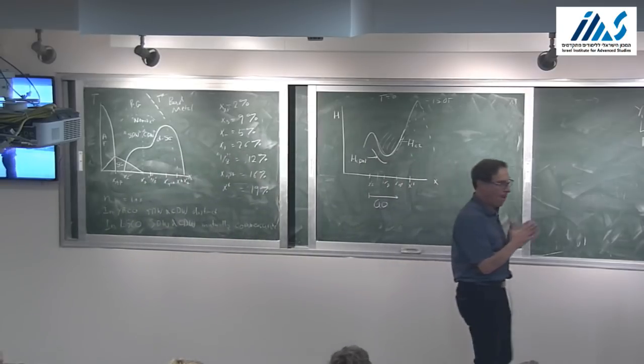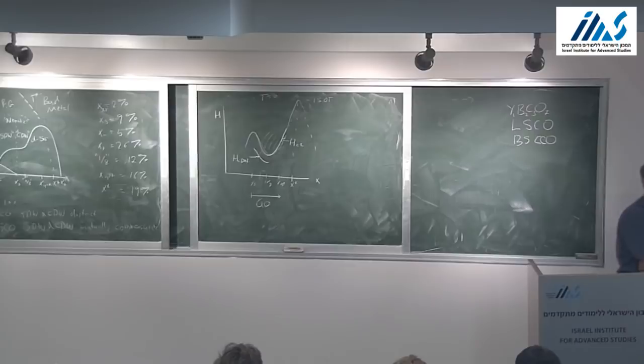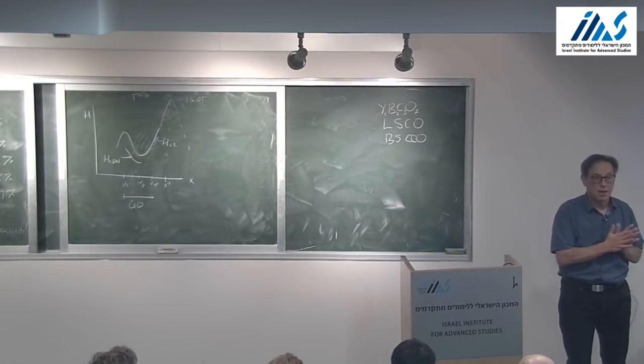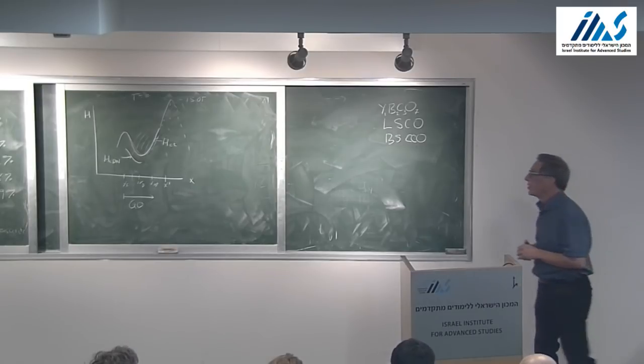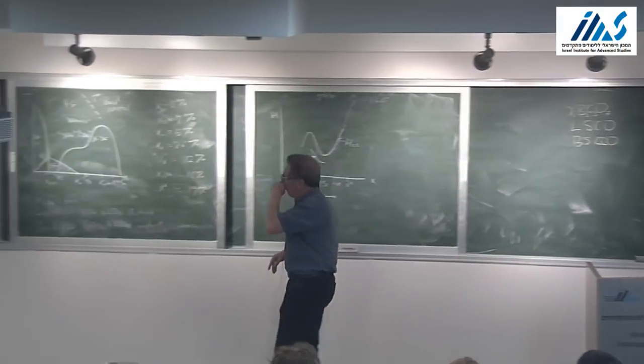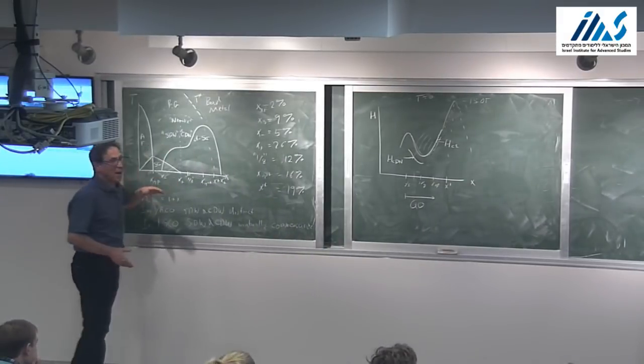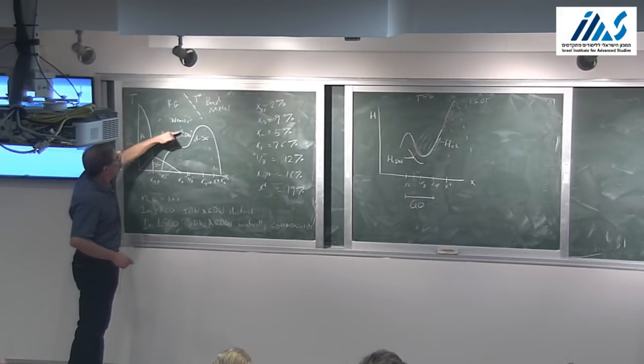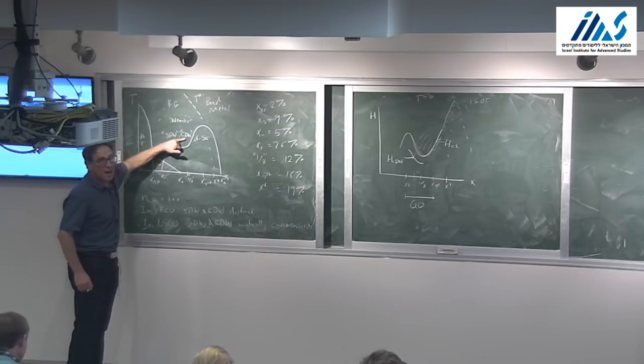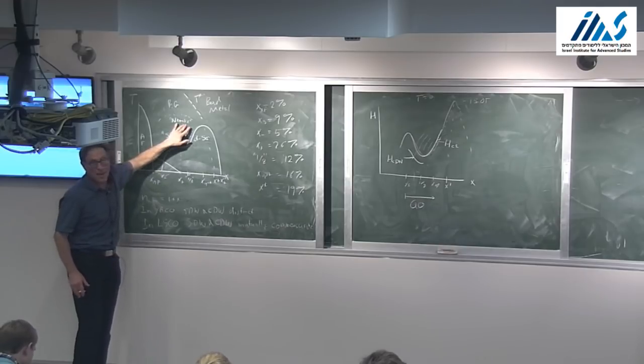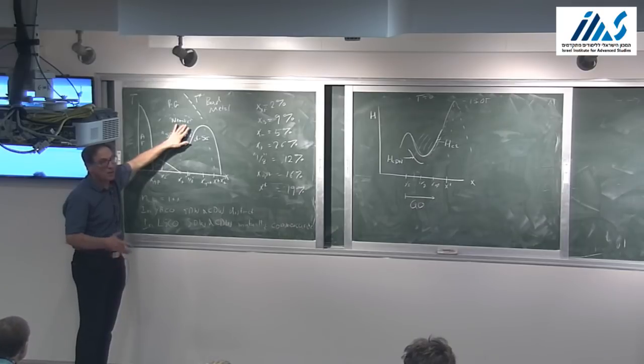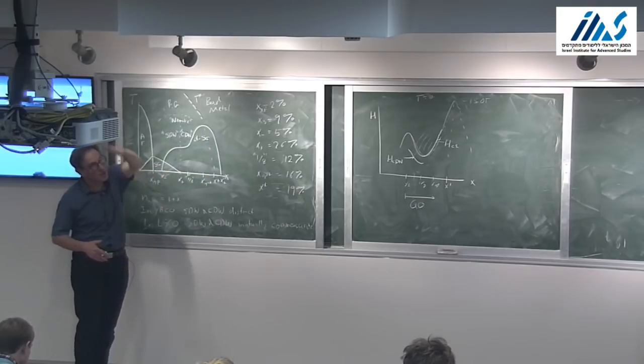Yeah. So how does one actually see this charge density wave transition, that it goes from some fluctuating order to some long range order? Is there a drastic change in the correlation length? There's a drastic change. So these are things I'm going to discuss in my next lecture, but here, if you look at the onset of charge density wave here, it's vague. It's basically where a peak that you see in a diffraction experiment comes up above a background. There's no singular temperature dependence to the charge density wave correlations. They just sort of rise up.